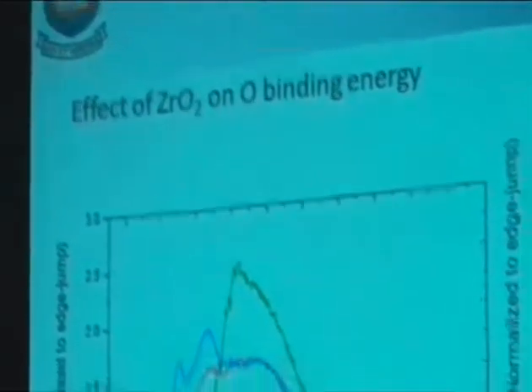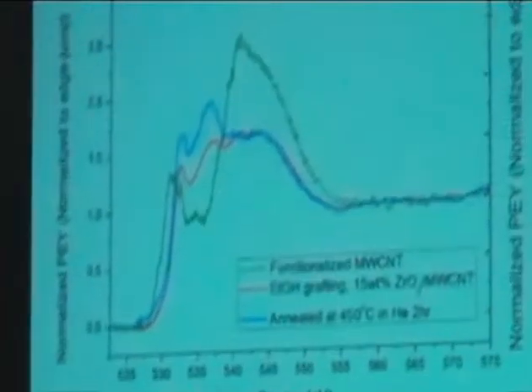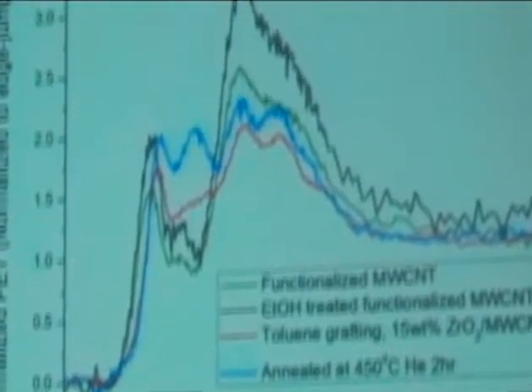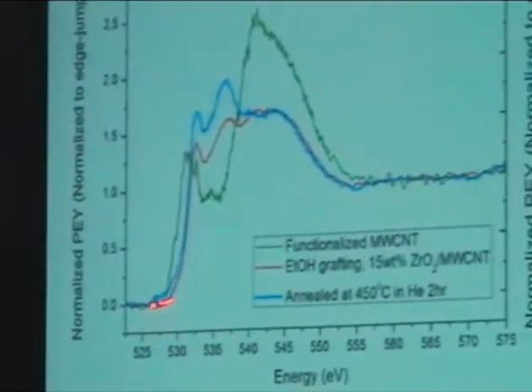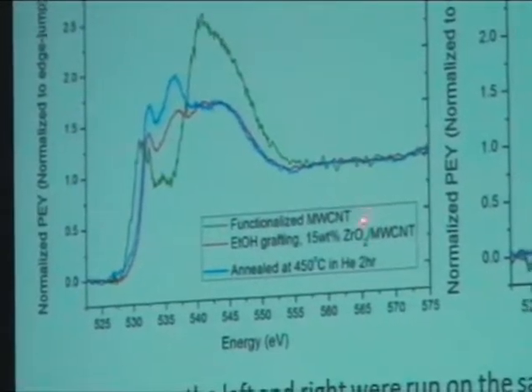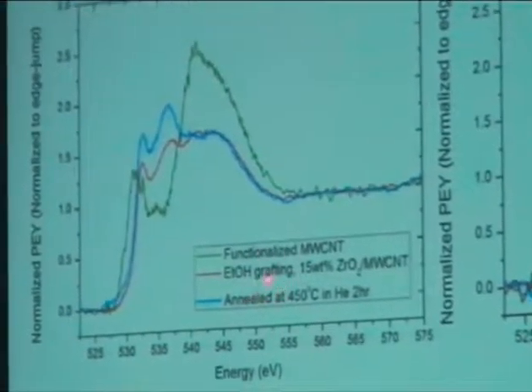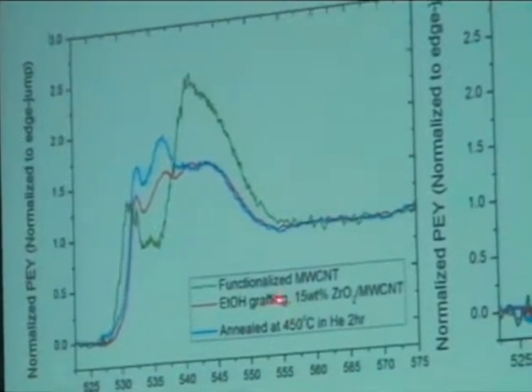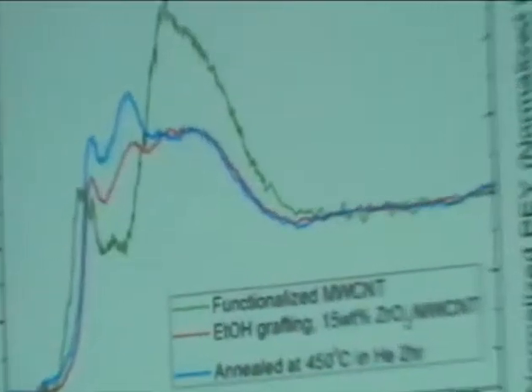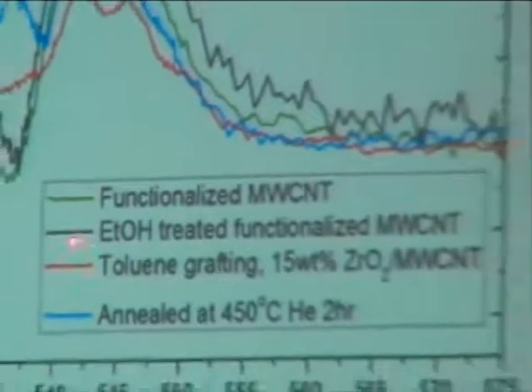how we're looking at 2 examples. These are oxygen K-edge absorptions. They're kind of dense, 2 kinds of spectra here, but I just want to draw your attention to 2 things. Over here we have the leading edge, which is at lower binding energy, for functionalized carbon nanotubes, or functionalized carbon nanotubes which have been reduced by ethanol at high temperature in the liquid phase. And they are at lower binding energy than when we have zirconia, which is shifted up. Here we've got the same situation where we've got a functionalized carbon nanotube, and then again one that's been reduced with ethanol, and relative to zirconia, where the carbon nanotubes have zirconia on them, there's a shift.